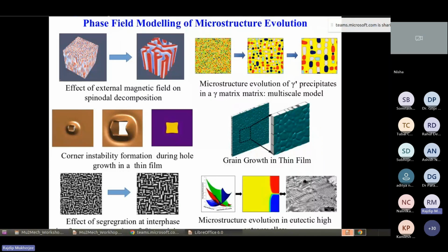But this is a liquid to solid phase transformation. Right now, our model is mostly for solid state phase transformation, but it follows a similar model in our software. So the phase field model is quite capable of studying eutectic solidification, both eutectic and off-eutectic. Off-eutectic means a slightly higher or lower composition, away from the eutectic point. You are basically interested in these two phases, one A-rich and one B-rich, and depending on the tie line, you can find out what these compositions will be for the eutectic alloy.